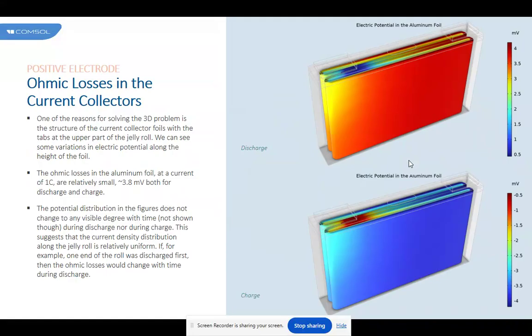Ohmic losses in the current collectors. One of the reasons for solving the three-dimensional problem is the structure of the current collector foils with the tabs at the upper part of the jelly roll. We can see some variations in electric potential along the height of the foil. The ohmic losses in the aluminum foil at a current of 1C are relatively small, about 3.8 millivolts, both for discharge and charge. The potential distribution in the figures doesn't change to any visible degree with time, neither during discharge nor during charge. This suggests that the current density distribution along the jelly roll is relatively uniform.